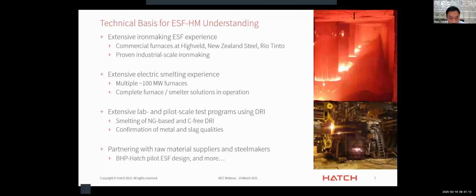Second of all, beyond just iron making electric furnaces, large, and by large I mean probably close to 100 megawatt furnaces, are very widely used in ferroalloy and non-ferrous applications. These are, scale-wise, equivalent to about 1.5 million tons of feed throughput a year, which is at the scale that the steel industry needs to apply this solution. There have been complete smelter solutions offered throughout our history, and of course throughout the entire metallurgical industry, to prove that not just the furnace itself, but the entire solution from off-gas system to raw material handling is available. And of course, all the strategies to implement this in reliable and consistent production and quality control are very, very mature.